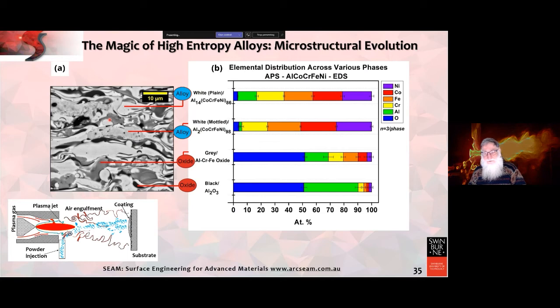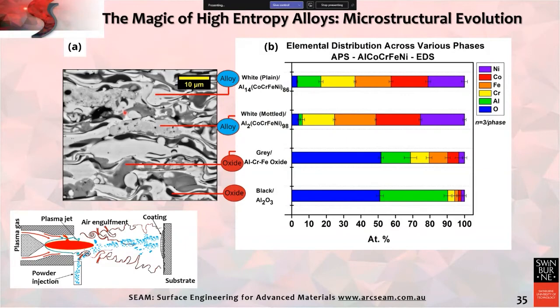It's not a secret, but what people don't realise is that many of the coatings which are used for corrosion protection are also impregnated with epoxies. So if there's porosity and the intention is to use it in a wet corrosion atmosphere, then epoxy will fill up all of the pores and give protection.